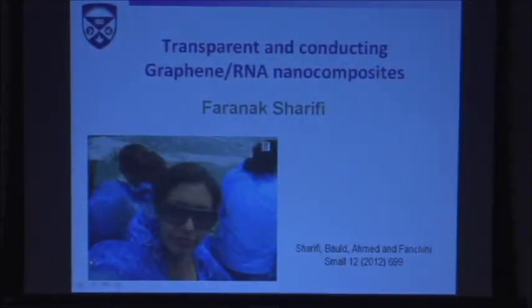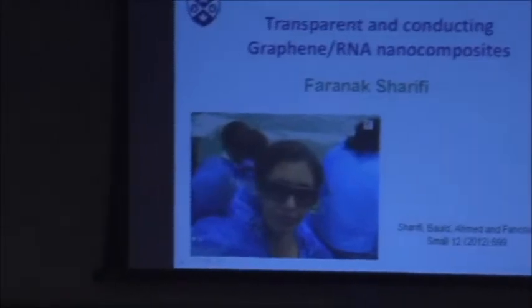I was mentioning before that when I left Rutgers, I decided to move a little away from graphene oxide, because there were a lot of defects. Defects lower the thermal conductivity, and defects lower the performance of graphene-based devices. Defects are related to the fact that I have to use a treatment that is quite close to the treatment of Brodie 1859 to oxidize graphene, to make it soluble in water and vacuum filtrate it spaghetti style. I still wanted to use the vacuum filtration method because it creates films, very scalable, with a lot of applications.